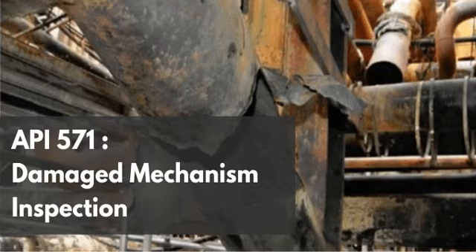Well, it comes down to the fundamental difference between thermal residual stress and mechanical residual stress. Okay. Think about manufacturing a carbon steel elbow or a reducer. You're taking a straight section of pipe and forcing it into a new geometry through severe plastic deformation. You're physically bending it into shape. Right. And unless this is done via hot forming above the recrystallization temperature or followed by a full normalization heat treatment, you are cold working the steel. You are permanently distorting the crystalline lattice across the entire body of the fitting. So the whole thing is just loaded with stress. Exactly.